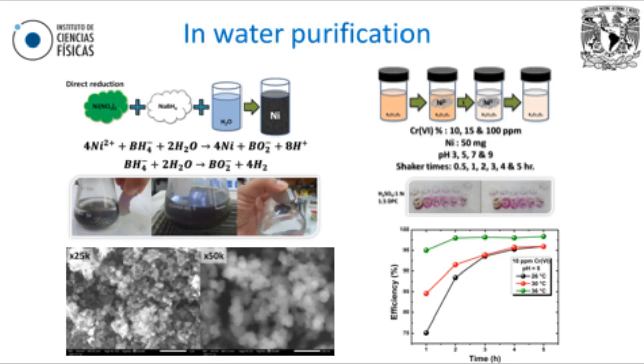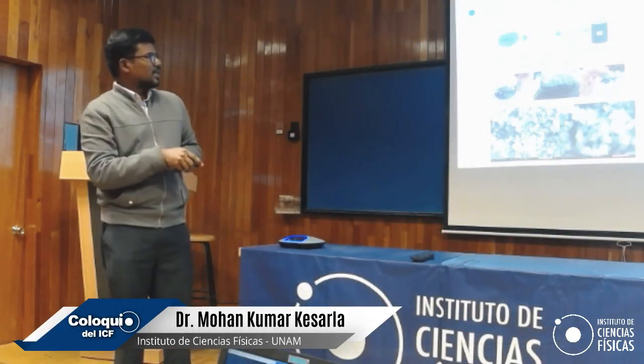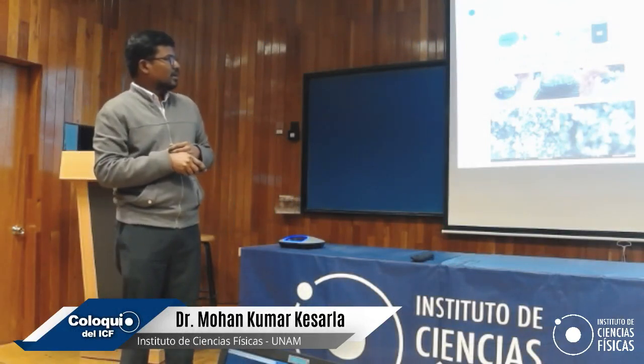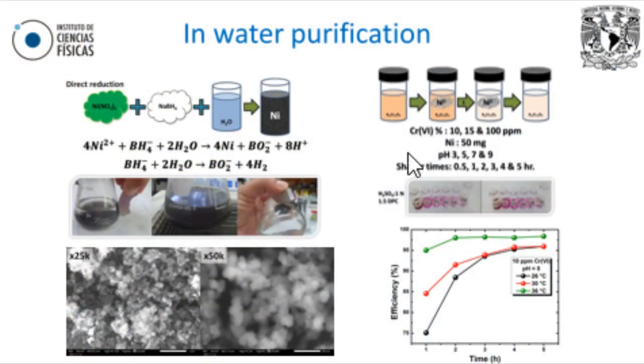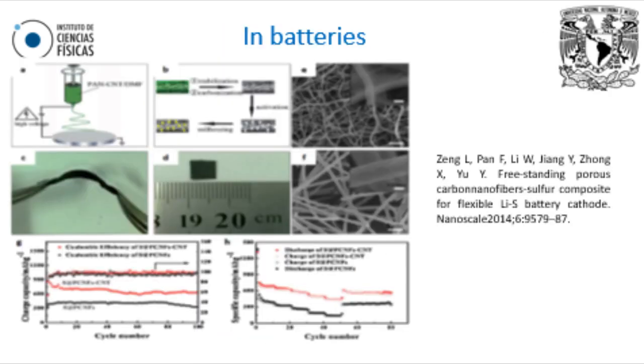If you want to analyze chromium, you can go for advanced techniques like atomic absorption spectroscopy or inductively coupled plasma optical emission spectroscopy. But since we don't have those, we went for a colorimetric technique. You take diphenylcarbazide, which makes a complex with chromium, giving various colors depending upon the chromium content. With time, the color decreased, which indicates that the chromium percentage is decreasing. So within 5 hours, we almost achieved 98% removal efficiency using these nickel nanoparticles, but this is without fibers. Then we incorporated nickel into the fibers.